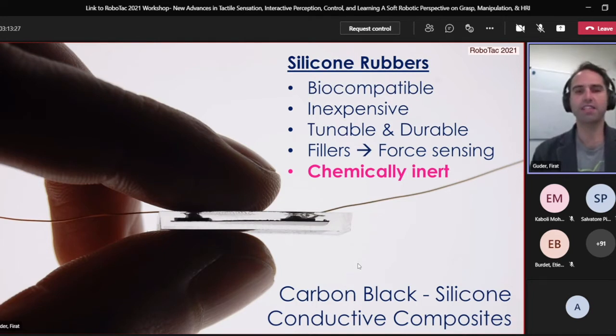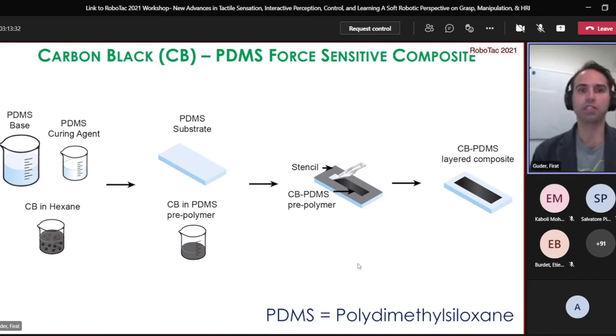But the way these sensors are created is fairly straightforward. Essentially, we just take a silicone formulation. In this case, it's PDMS, and then we mix it with carbon black particles, and then this becomes an ink, and then this could be printed on a stretchable substrate. And once the ink cures, because this is the prepolymer, so it still needs to cure to become the final stretchable material, it's kind of ready to use.